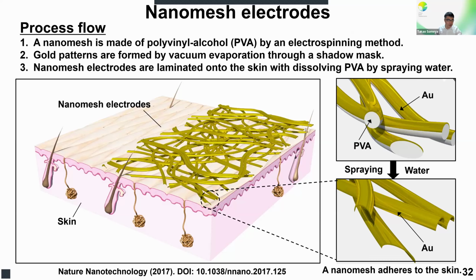And this slide shows you the fabrication process of the nanomesh electrode. First, nanomesh is made of polyvinyl alcohol, which is known as a water-soluble polymer, by an electrospinning method. And then gold patterns are formed by vacuum evaporation through a shadow mask. And the nanomesh electrodes are laminated on the surface of skin with adding some water by spraying. So PVA is dissolved into water and washed away completely. Finally, a porous gold thin film remains on the surface of skin.